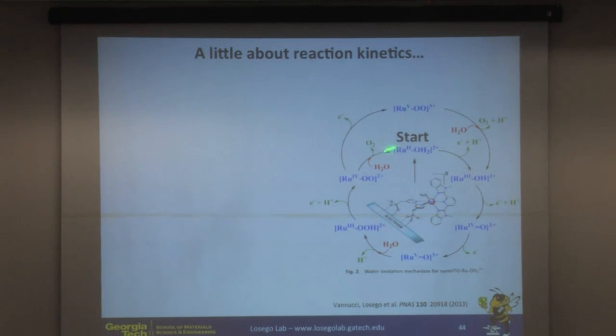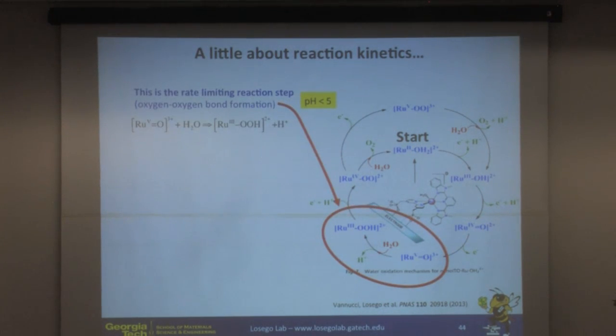So if we go back and look at the mechanism for this oxidation catalyst, this is the rate limiting step right here. The rate limiting step is essentially when you add the second water molecule to your catalyst site, and during this process you're forming the oxygen-oxygen bond. So you need to add an OH group to this ruthenium 5 complex.